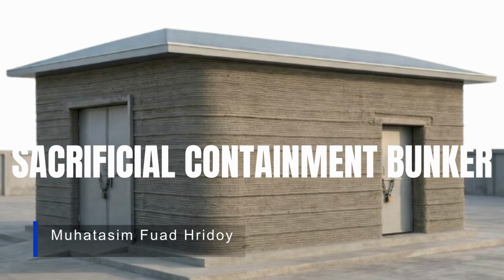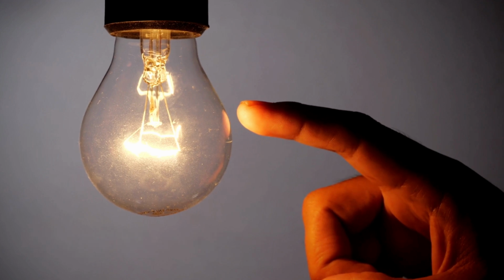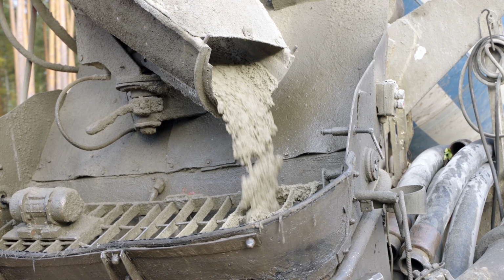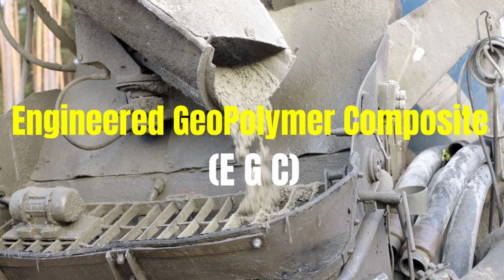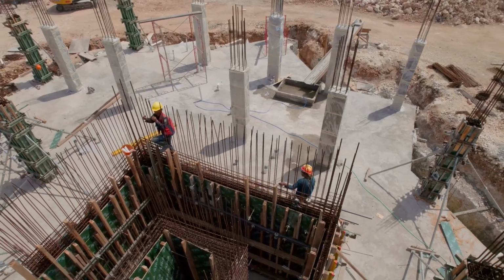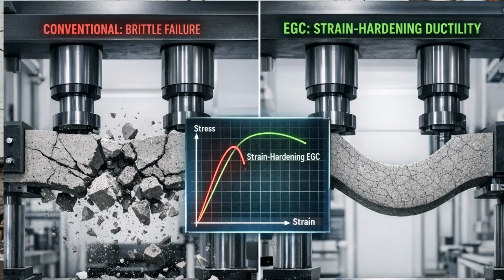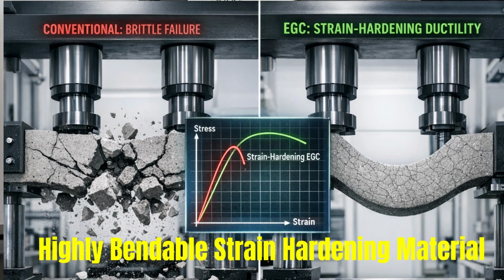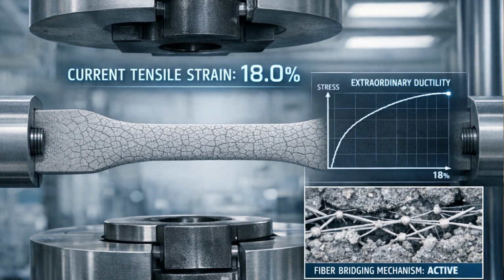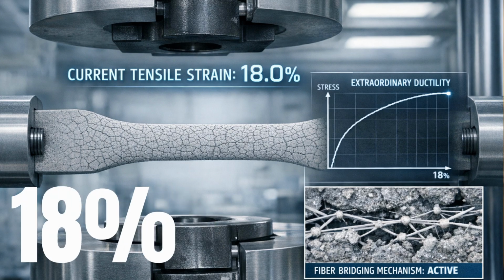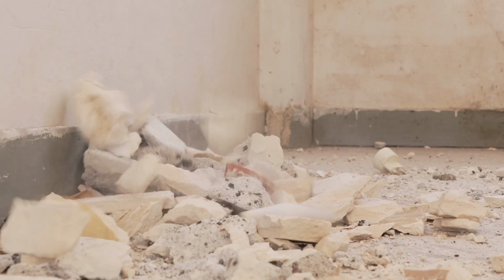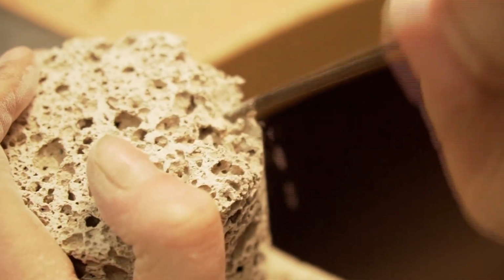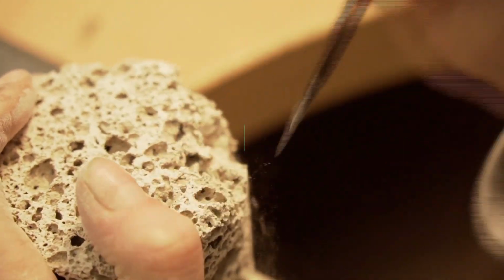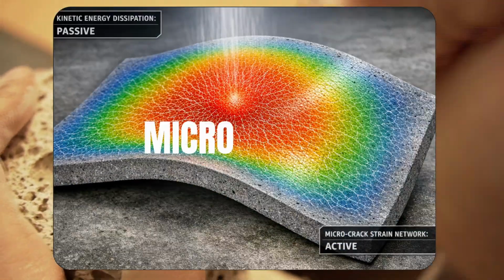Introducing the sacrificial containment bunker. The core of this innovation is the material itself, engineered geopolymer composite, EGC. Unlike conventional concrete that shatters under pressure, EGC is a highly bendable, strain-hardening material. It possesses an extraordinary tensile strain capacity of up to 18%. Instead of failing violently, it absorbs kinetic energy by distributing stress across thousands of tight microcracks.